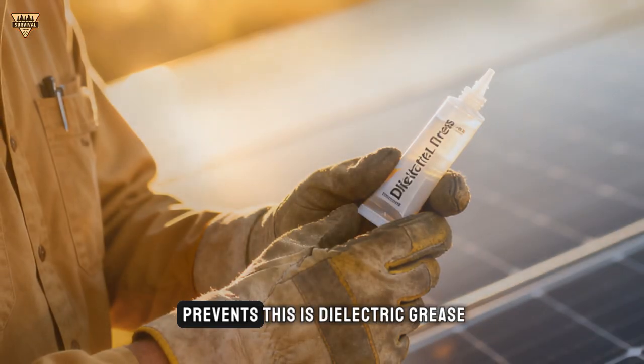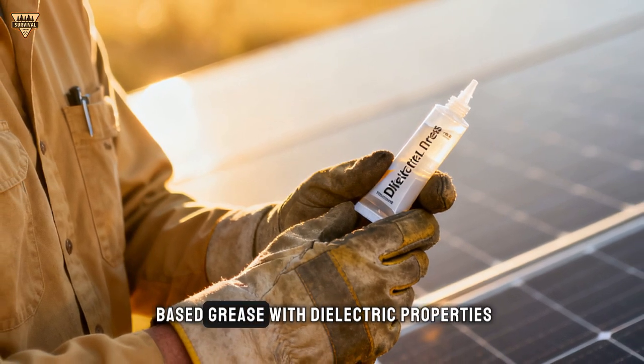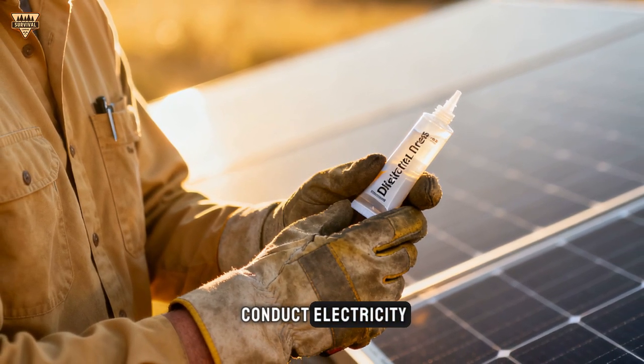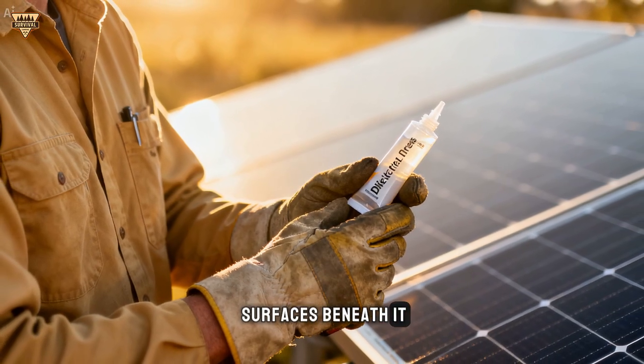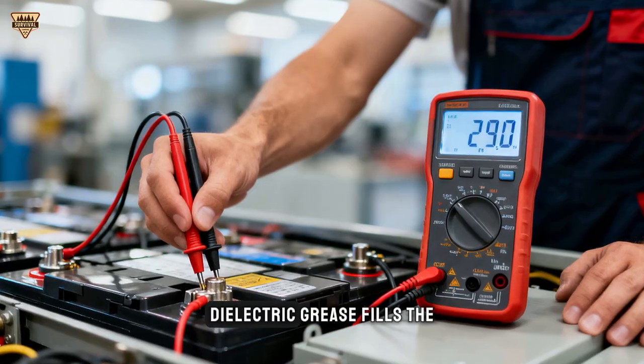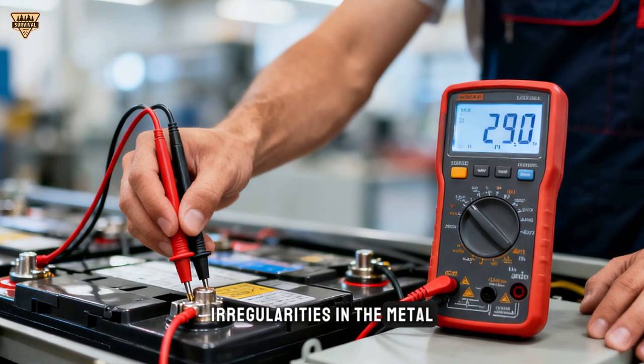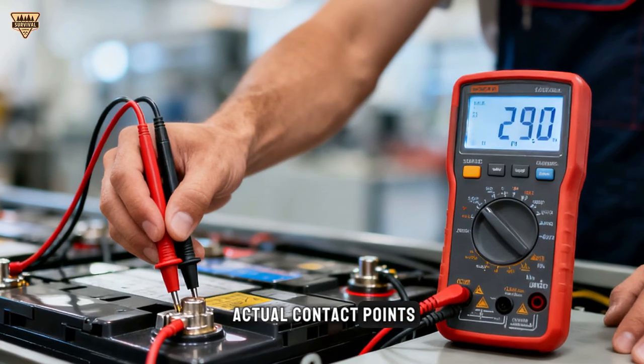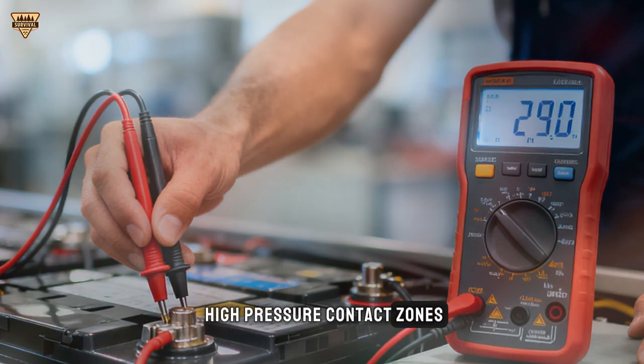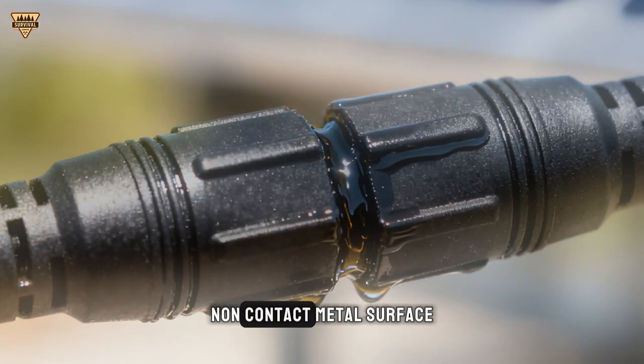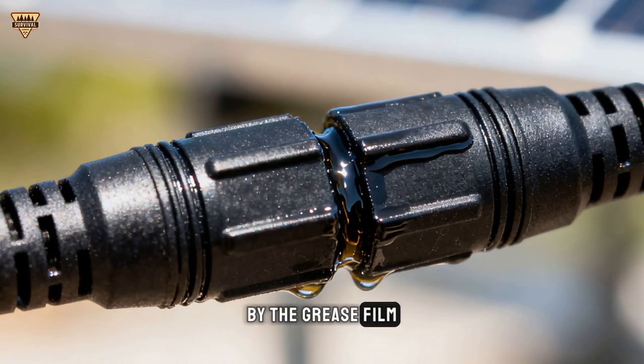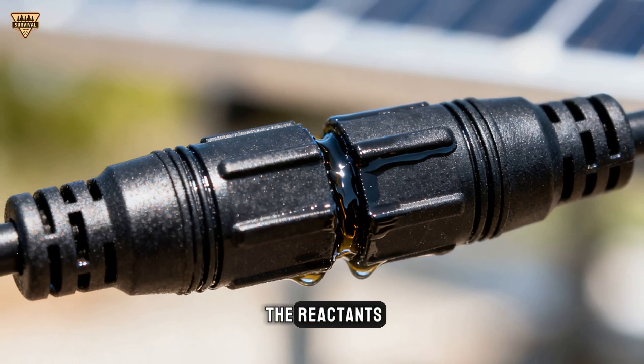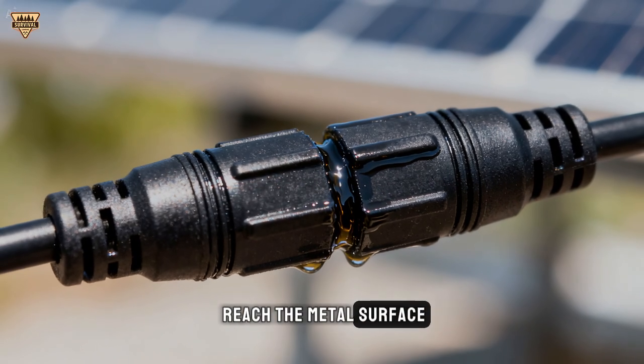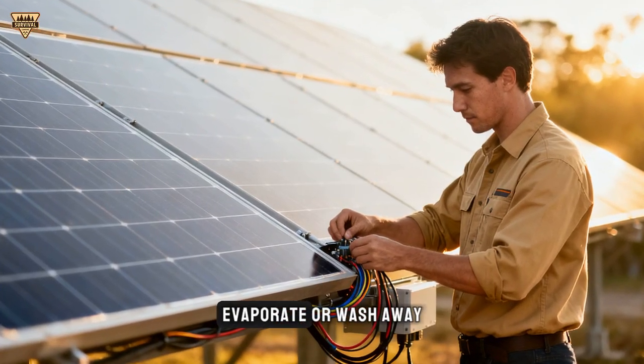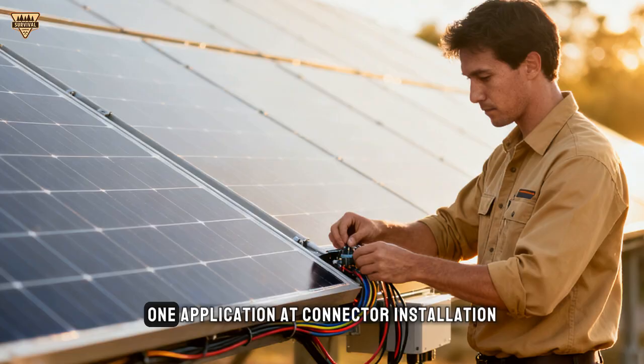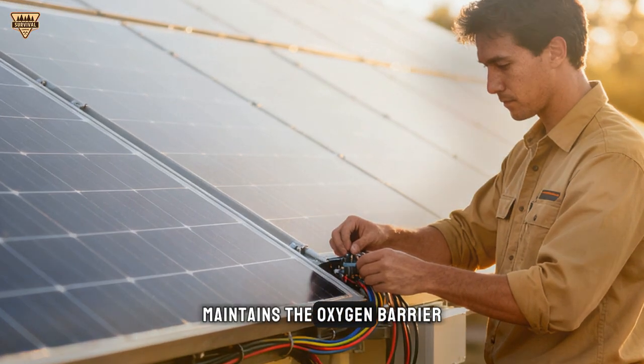The compound that permanently prevents this is dielectric grease, a silicone or synthetic base grease with dielectric properties, meaning it does not conduct electricity, but blocks the passage of oxygen and moisture to metal surfaces beneath it. When applied to connector contacts before mating, dielectric grease fills the microscopic surface irregularities in the metal. Metal-to-metal contact still occurs at the actual contact points. The grease displaces from high-pressure contact zones, maintaining electrical conductivity while the surrounding non-contact metal surface is sealed from oxygen and moisture by the grease film. Oxidation cannot begin because the reactants, oxygen and moisture, cannot reach the metal surface. The silicone base of dielectric grease does not degrade, evaporate, or wash away under normal environmental conditions. One application at connector installation maintains the oxygen barrier for the life of the connector.